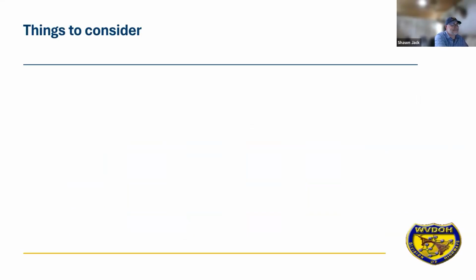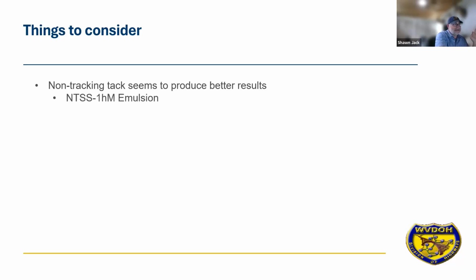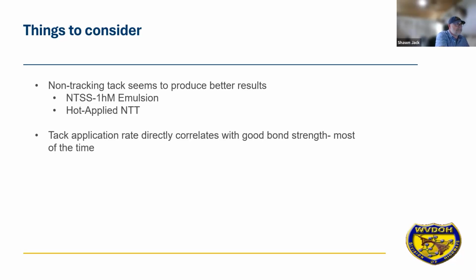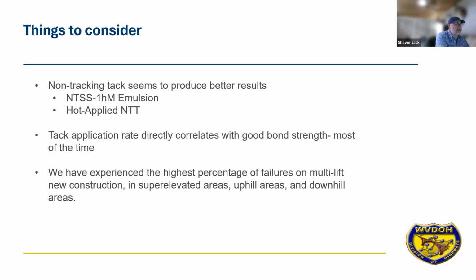All right, some things to consider. In our experience, non-tracking tack seems to produce the best results. We see a lot of the NTSS1HM emulsion that Randy mentioned. We do also see some hot applied non-tracking tack. Tack application rates correlate with good bond strength most of the time. And we have experienced the highest percentage of failures on multi-lift new construction pavements, which we said earlier, as we tend to see better bond strength in milled areas, and also in super elevated areas, uphill areas, and downhill areas.